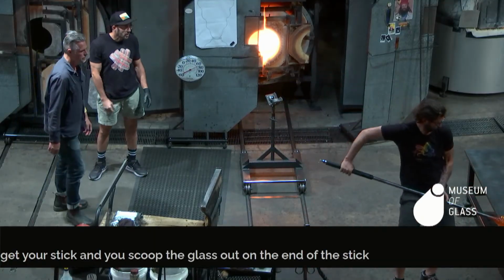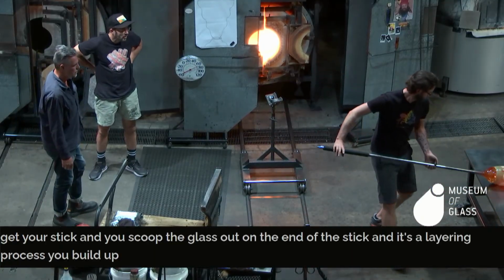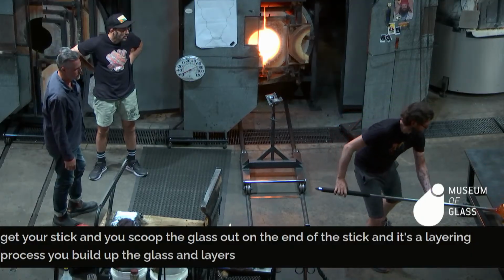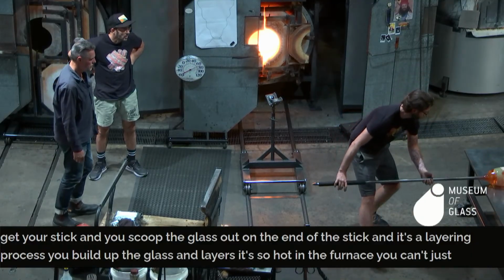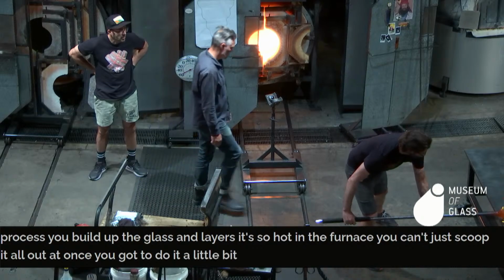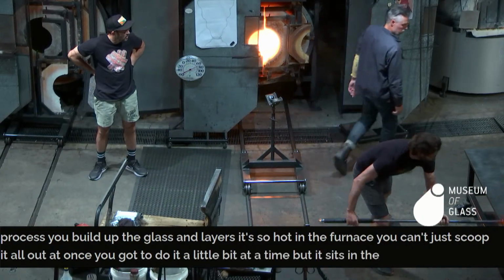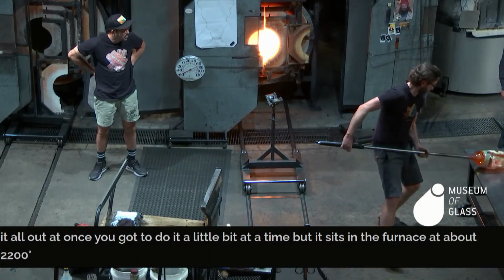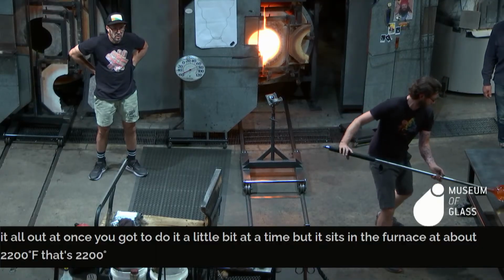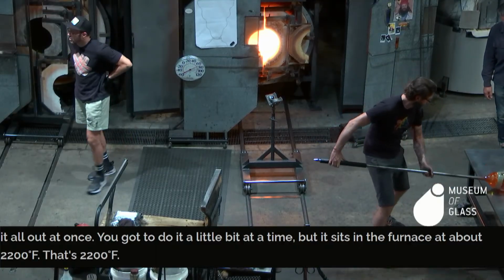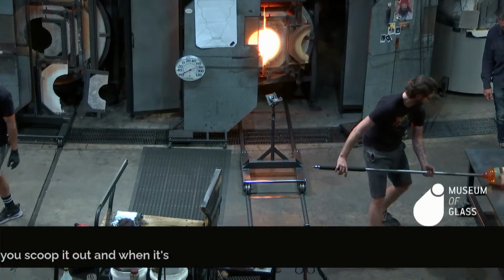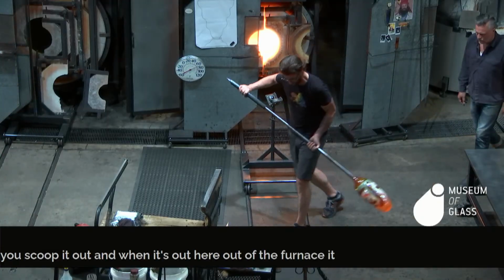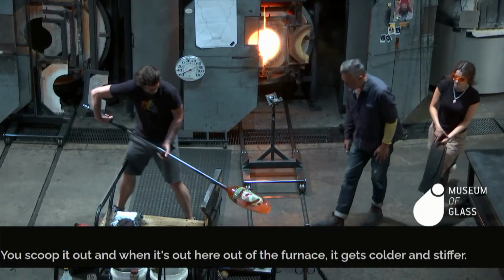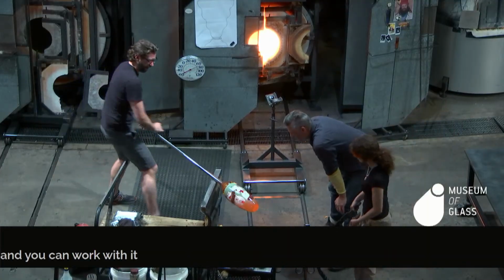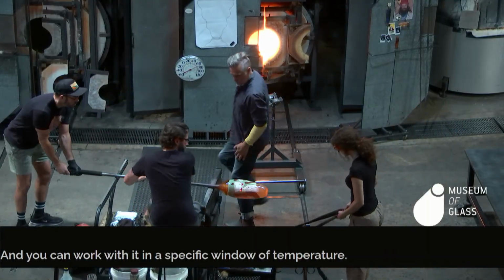And it's a layering process. You build up the glass in layers. It's so hot in the furnace, you can't just scoop it all out at once. You got to do it a little bit at a time. But it sits in the furnace at about 2,200 degrees Fahrenheit. That's 2,200 degrees Fahrenheit. You scoop it out, and when it's out here, out of the furnace, it gets colder and stiffer. And you can work with it in a specific window of temperature.